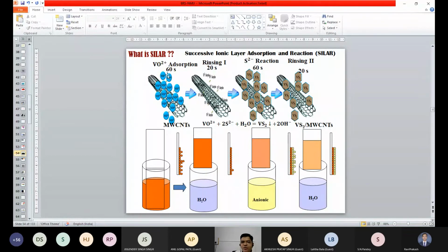And then the VO2+ is reacted with S2- ions. So finally, you get vanadium sulfide on the carbon nanotube. And interestingly, the carbon nanotube is coated on stainless steel. We have deposited vanadium sulfide using the SILAR method, that is, the successive ionic layer adsorption and reaction method. And most important, the vanadium sulfide we obtained has a hexagonal shape. That is the interesting thing. Why hexagonal shape, I can explain in the next slide.